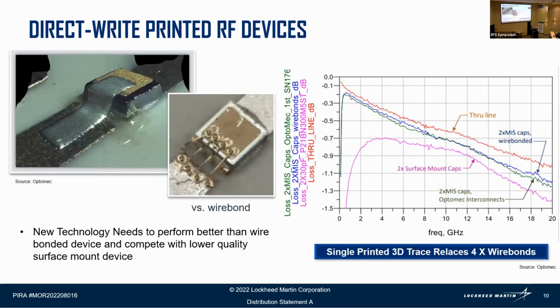This is another example. Not only do we do bare die ICs, but we also have several different components that we're looking at. What you can see here is what we call a MISCAP, and it's got a little capacitor that we bond down using conductive epoxy. Then we again print a dielectric ramp, and then we print the interconnect over the top of the device. And then you can see in the middle the wire bonding version of this device.